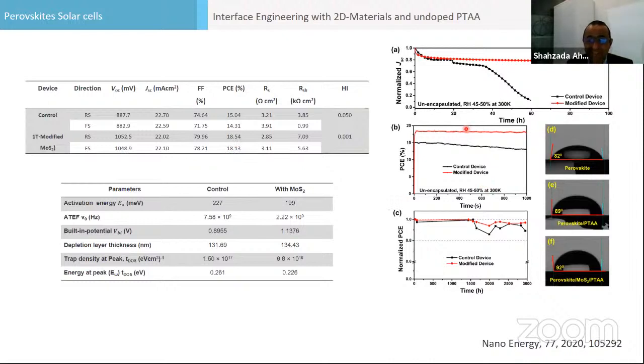The good thing was these devices were very, very stable, because 2D material like graphene or MoS2 are very rigid materials, so they protect the perovskite layer. And why does it happen? Because the hydrophobicity of the surface has increased, and the surface became more hydrophobic, so they were more resistant to environmental attack from the moisture, and the devices perform very well. You see, this is maximum power point tracking. The red curve is with 2D material, this is without 2D material.